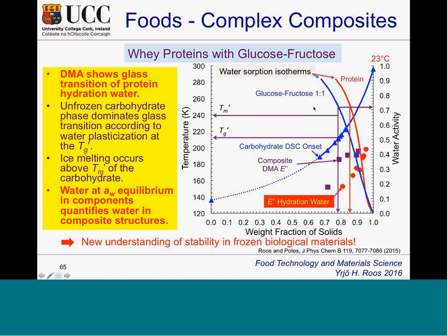We put the sorption isotherms of those together with the transition curve of a mix and hydration water. We could quantify how much water was in the protein at the maximum freeze concentration and how much was in the carbohydrate fraction. And we say that protein with this water content has that and that much water to freeze out from the protein, with how much it dehydrates in freezing. And we could say when the water gets to the glass, etc. These are fundamental axes for conservation studies that should take that on board.